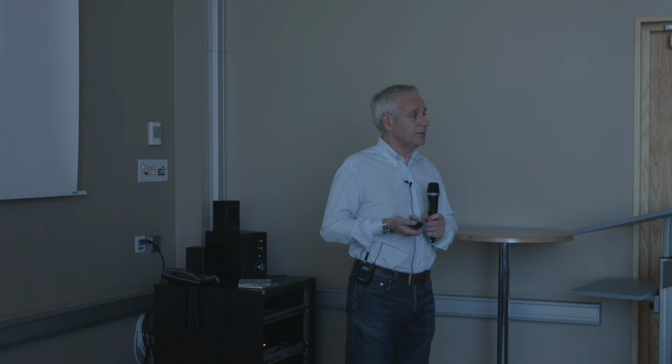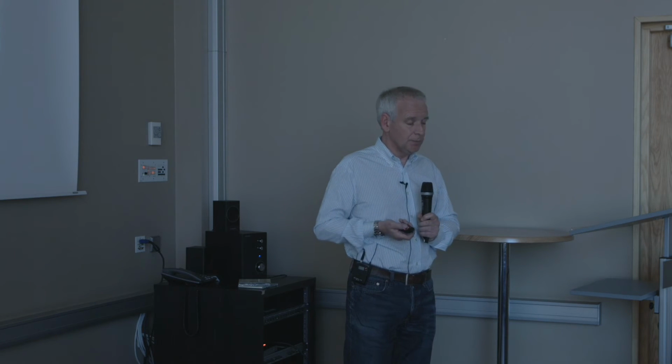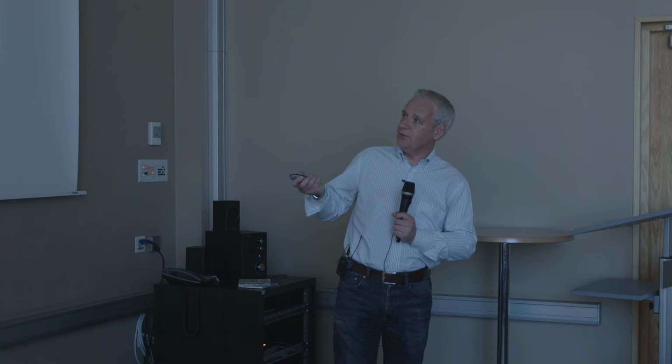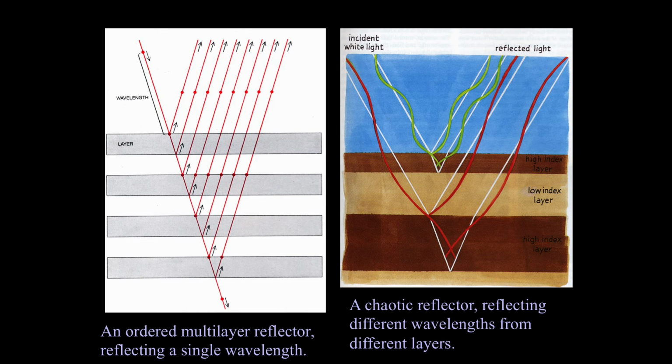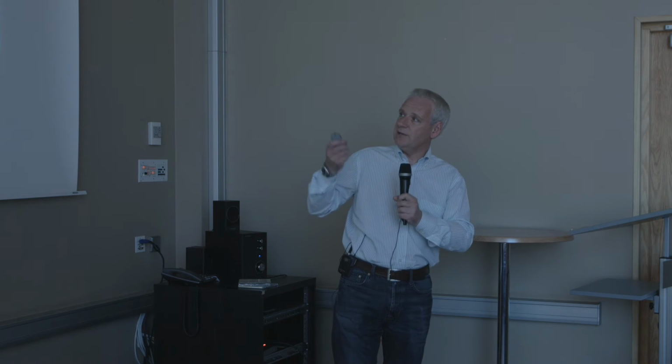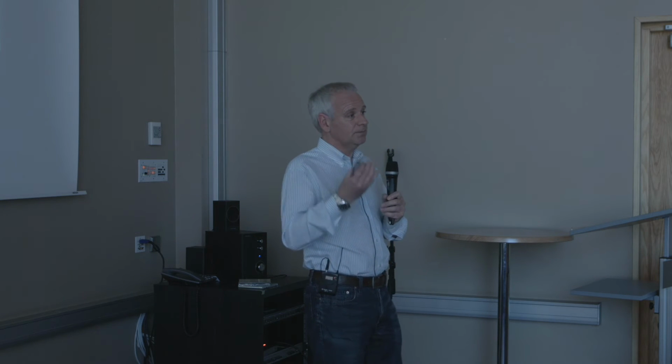So those colours I've been talking about mainly are single wavelength colours. They're producing a single hue when we've got a stack of thin films like that. But if we actually make the layers different thicknesses, then each one of them will be responsible for reflecting a different wavelength in that same direction. And eventually all those wavelengths can overlap to form silver, a broadband colour, maybe even gold or copper. We're finding some of those now in chromatophores.